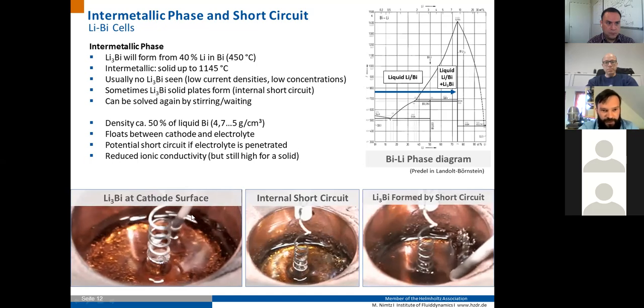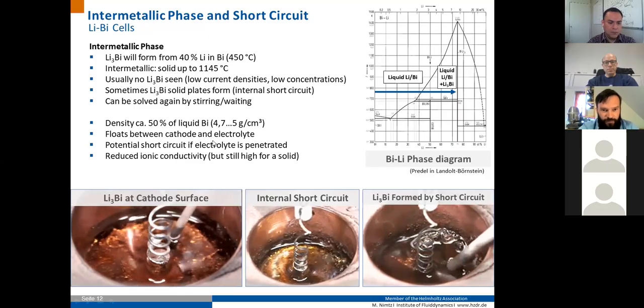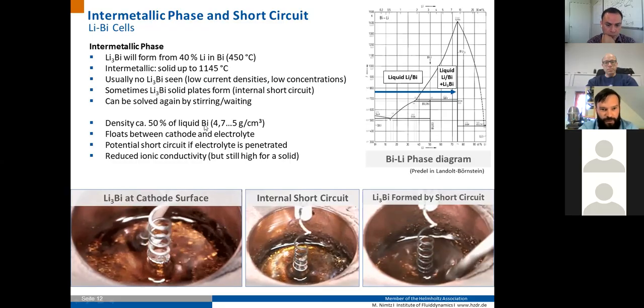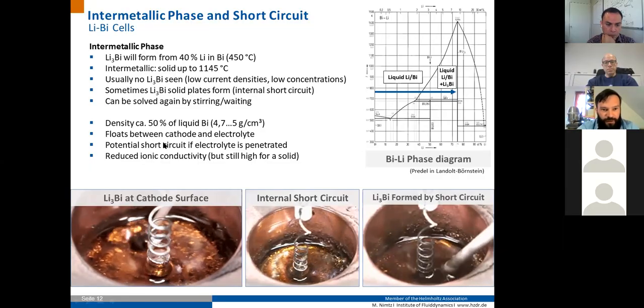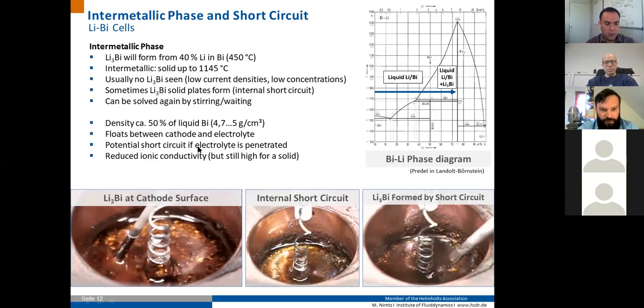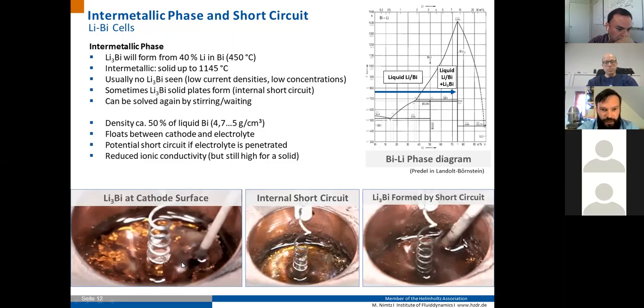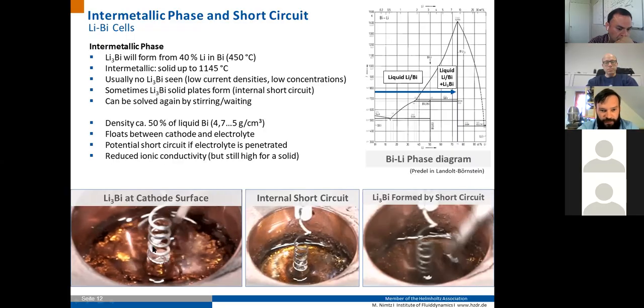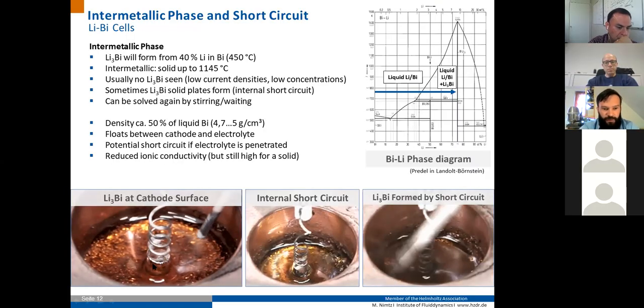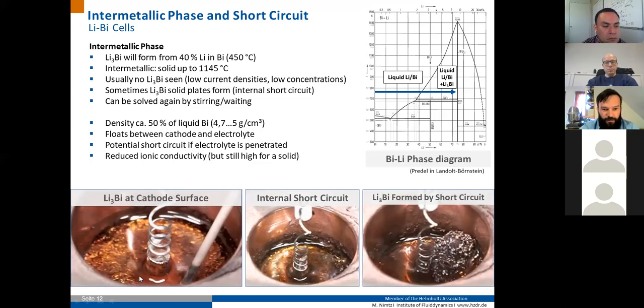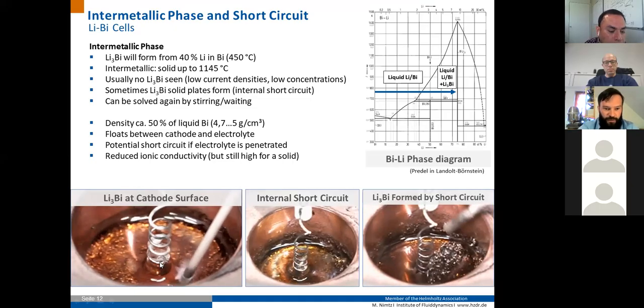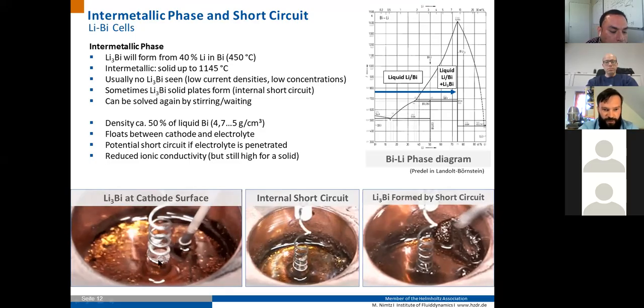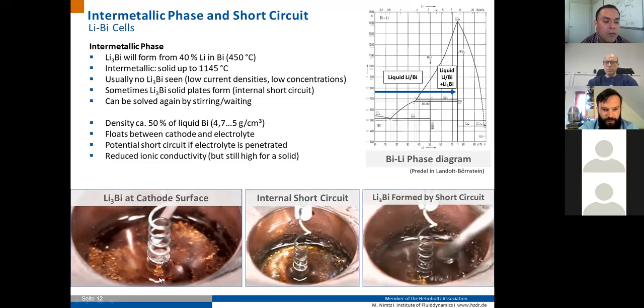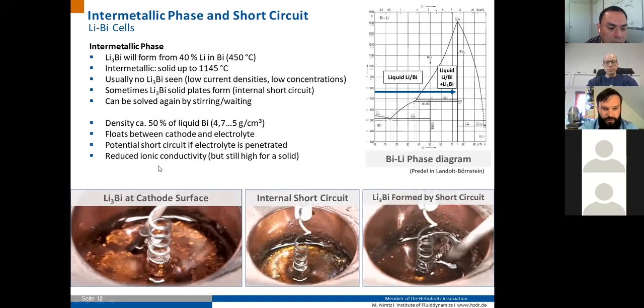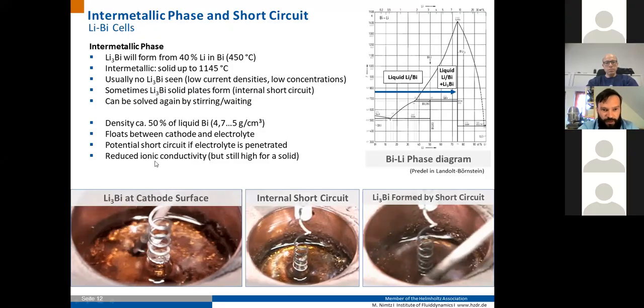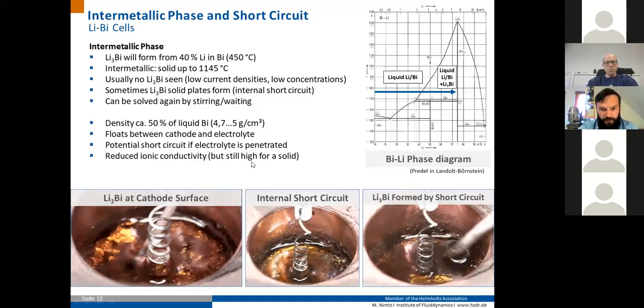The intermetallic phase has a density of around 5 grams per cubic centimeter. This should read Li3Bi. And this means the intermetallic phase will float between the cathode and the electrolyte, because cathode density typically is around 10, electrolyte density maybe around 2.5 to 3, and the intermetallic phase is between, so it will stick at the surface of the lower electrode and then lead to problems. Potentially, there could be another short circuit if the lithium electrode is not fully dissolved in the lower electrode. And as I said, we not only have a lower diffusivity, but also a lower ionic conductivity, which will lead to lower current densities during discharging.